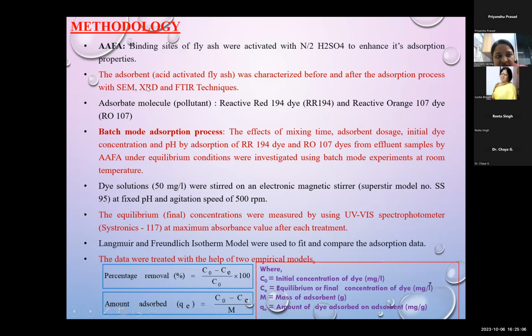The methodology used in the study is, first of all, the binding sites of fly ash are activated with H2SO4 to enhance its adsorption property. The adsorbent, that is activated fly ash, was characterized before and after the adsorption process with SEM, XRD, and FTIR techniques. Adsorbate material, that is pollutant, we have collected two types of dyes. First is reactive red 194 dye and second is reactive orange 107 dye.